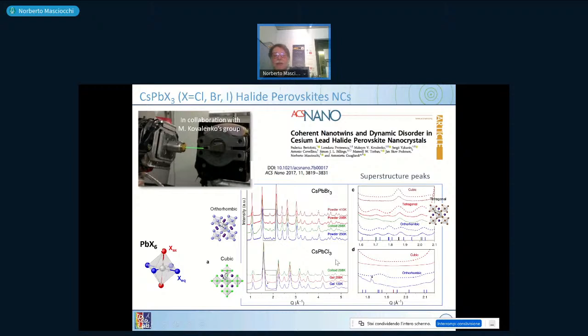If you go to cesium lead chloride, apart from this tiny peak which was given by some condensation, freezing water, this is ice forming on the capillary, then you see that there is no trace for the cubic system and hardly anything visible for the orthorhombic one. So here you have something visible because these peaks are very tiny, and distortion gives less information on these superstructure peaks. So that is it.